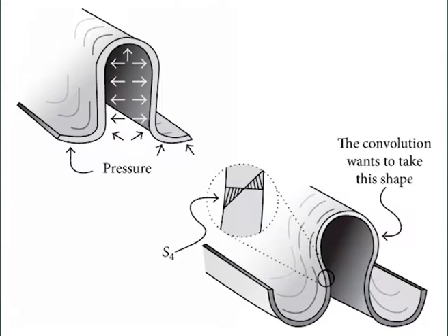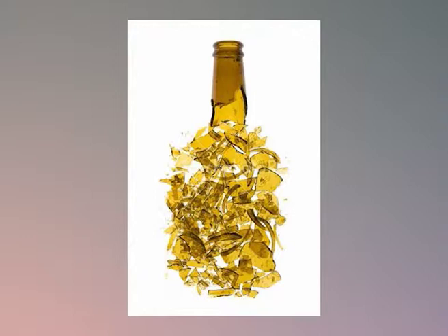If a glass container fractures due to excessive internal pressure, the typical fracture appears as a straight vertical split in the side wall of the container, which may be due to excessive carbon dioxide in beverages, thermal expansion of liquids due to heat, or generation of gas due to decomposition of contents. It usually originates at the heel or bottom where stresses are greater. These rarely originate in the neck of the bottle, as the neck is stronger than the side wall.